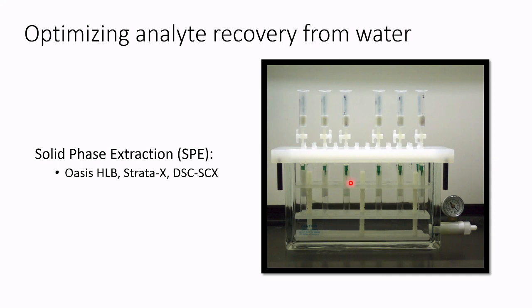Typically, when you're selecting SPE cartridges, you would go with properties that are consistent with what you're looking for. So for instance, if I have a cation that I'm targeting, then I would probably get a solid phase that's a strong cation exchange resin so that I can capture cations. Unfortunately, because we don't know what it is that we're looking for, we had to take a little bit of a step back and use a more broad screen approach. So what we used is the Oasis HLB